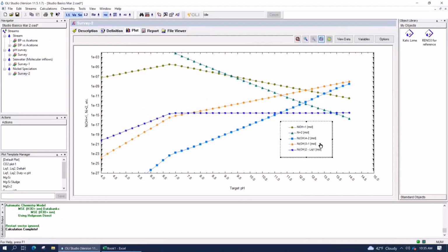Sure, absolutely. There's another piece to this discussion in the full 2-day class. What we would do is take this example, and then add either ammonia or cyanide to it. And what you would see is that the whole solubility of nickel or some other transition metal would be completely disrupted, because ammonia and cyanide create new dissolved complexes with the nickel, and it increases the solubility significantly. We won't do it here, but that's part of the larger discussion about the behavior of these transition metals in water with certain cations and anions.